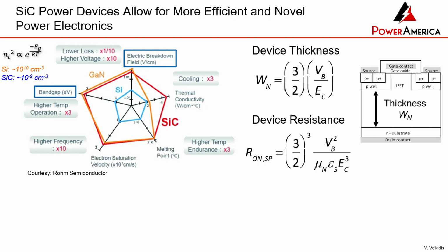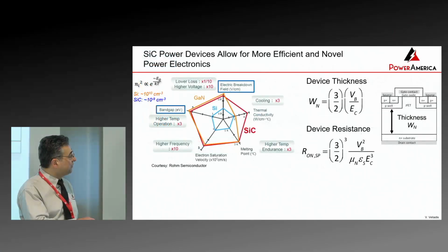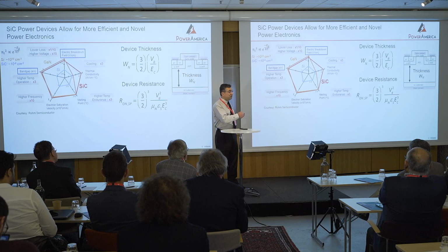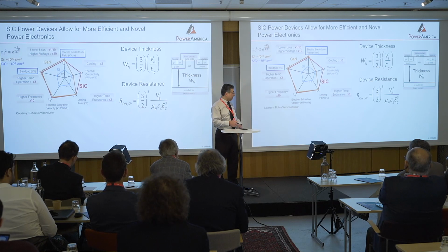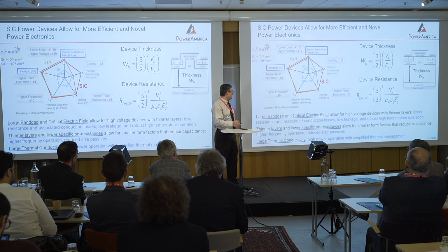So with respect to a device, if you look at this thick layer that holds the high voltage, the thickness of that layer is inversely proportional to the critical electric field. So if your critical electric field is 10 times higher, your device will be 10 times thinner for the exact same breakdown voltage capability. And if you look at the device resistance of this thick layer that holds the high voltage, it's inversely proportional to the third power of the critical electric field. So if your critical electric field is 10 times higher, then the resistance in principle can be 1,000 times less. So what does that mean?